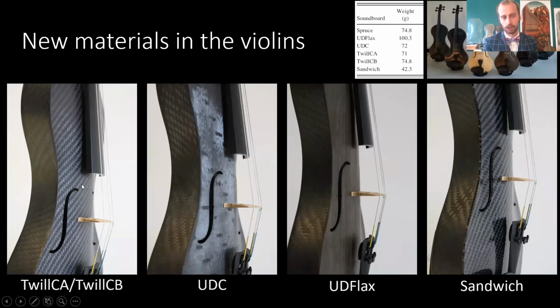One I made 2 times, which had this one, twill CA and twill CB. They have a unidirectional carbon fiber inside, but the outside is a woven carbon fiber. You have unidirectional carbon, so all the fibers are in the same direction, or almost all the fibers. You have UD flax, so this is unidirectional flax fibers. And then you have a sandwich material. So this sandwich material is the combination of a very thin carbon fiber sheet, 0.2 millimeters, together with a core material, which is in this case a Nomex honeycomb, about 1.5 millimeters thick. So these are all calculated and made to have the same stiffness along the axis of the instrument, but because there are different materials, the end result, the weight of the soundboard, is very different.